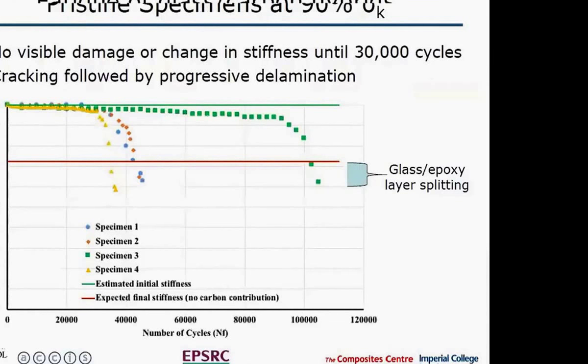Sorry, before we get to that point, I've got some results here which show what happens at 90% of that knee point strain. At 90% of the knee point strain, we see initially no visible damage, but after about 30,000 cycles, we do see some degradation. So at 90% of that knee point strain, we're a bit close to the limit. Although we haven't really seen the start of that major fragmentation, we're quite close to it.